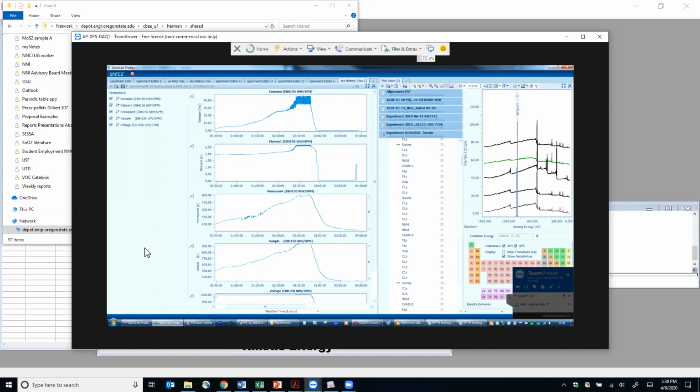Yeah, I remember there is some work on molyselenide and probably also molytelluride, where some types of defects, they call them wagon wheels or twin grain boundaries. From the STM, they show that those defects are very active and very reactive. They did HER, but I'm wondering if someone already did it on that.